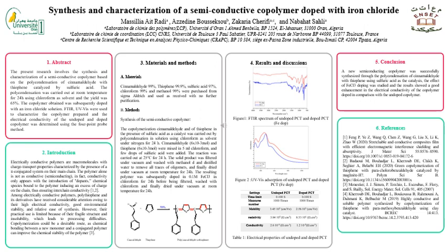To conclude, we can say that we have successfully synthesized a new conducting copolymer using the polycondensation of cinnamaldehyde with thiophene in the presence of sulfuric acid as the catalyst. The effect of iron chloride doping was studied, and the results showed a good enhancement in the electrical conductivity of the doped copolymer in comparison with the undoped one.